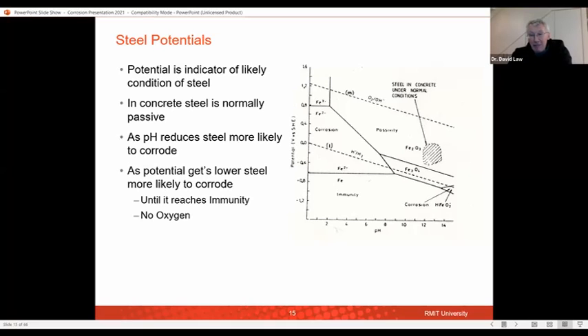However, if we have a drop in our pH, or we have chloride ions coming into the system, we move from a passive region into an actively corroding region. And so we move from this passive zone into this corroding zone. And so that is why we start to get corrosion. And so thus, as the chloride ions increase, or the pH drops, which happens when we have carbonation attack, and that neutralizes our pH in the concrete, we move into our corroding area. And that's where our Fe wants to move to our Fe2+. And so that is a problem that we've got.